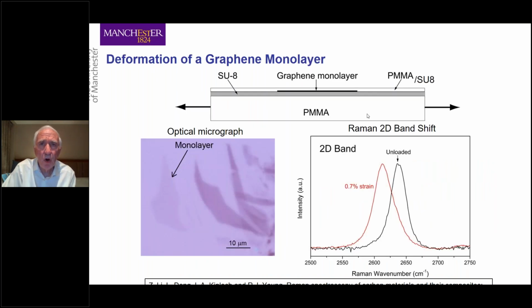And here you can make a sort of model paint, shall I say, which is thin films of polymer sandwiching graphene monolayers. So again, it's a similar sample here of a monolayer of graphene, which you can see in the optical microscope quite nicely, 10 micron scale here. And if you stretch the material, stretch the substrate in which the paint is sitting, you get this very large shift in the Raman band. So this is the essence of a strain sensor, this big Raman band shift. And that allows us to measure strain in a non-contact way. We don't need any wires. We can just shine a laser on it and we can measure strain.